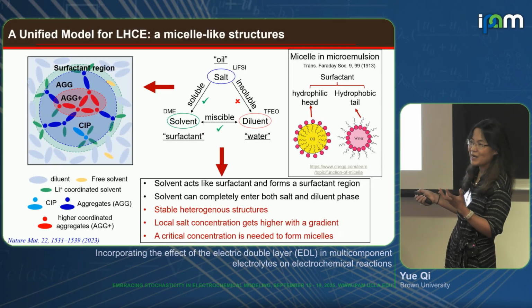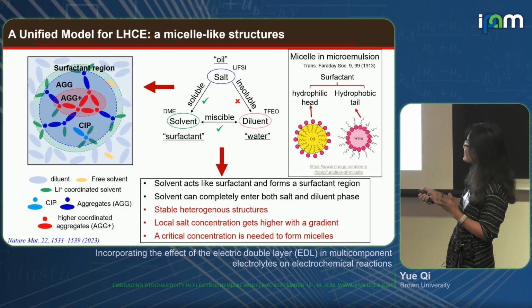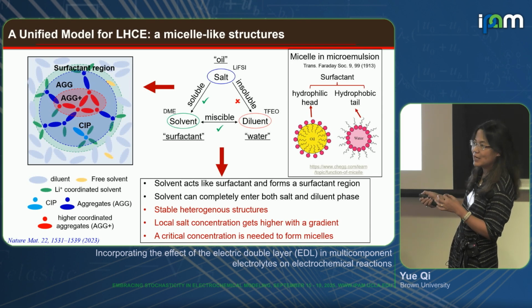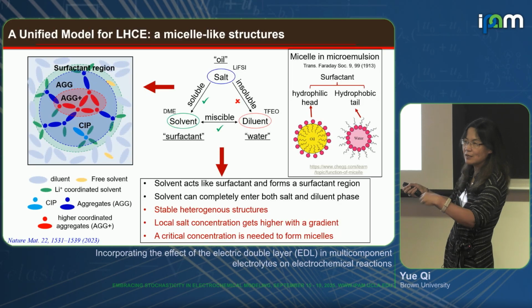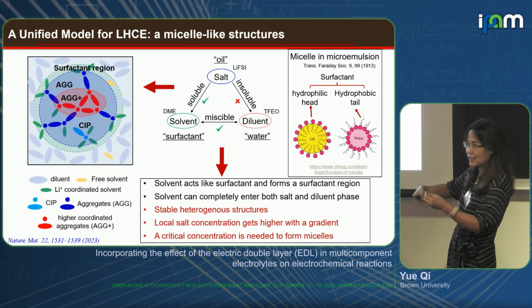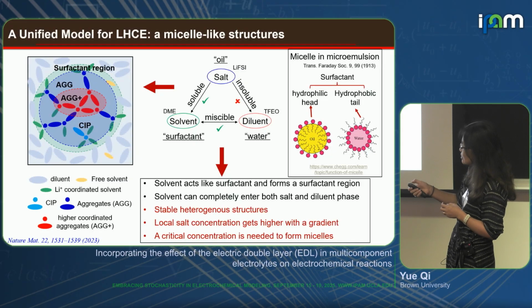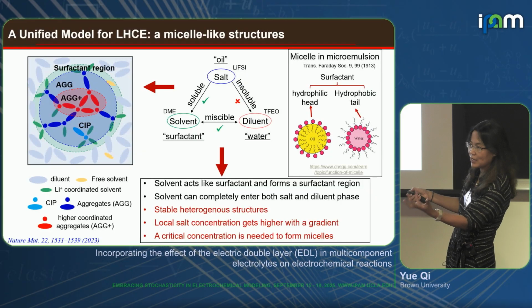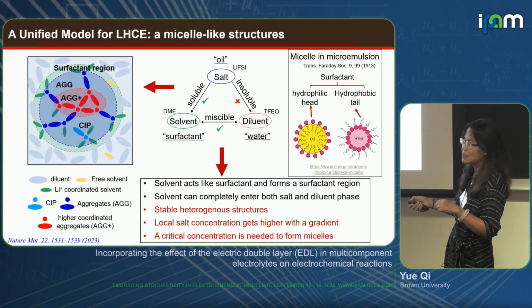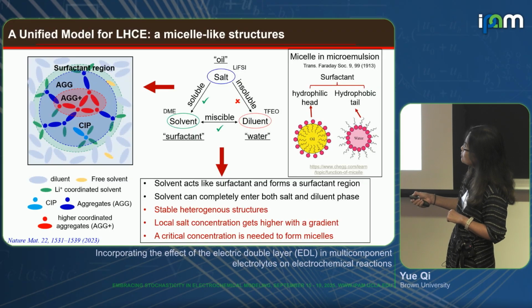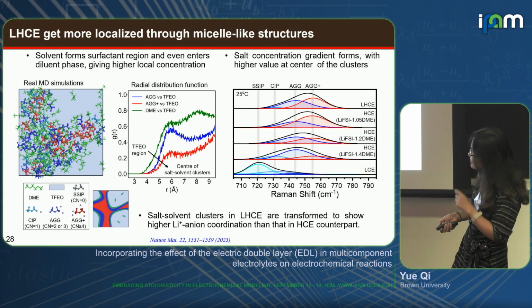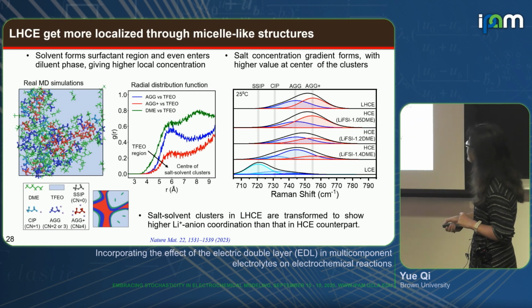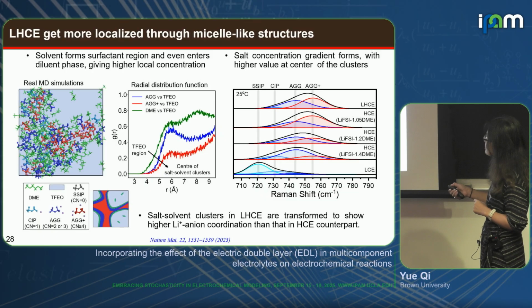But if you think about micelles, you know they don't collapse, right? This is a more stable structure. Our solvent actually is the peacemaker. It binds with the salt, and also likes the diluent, so they will naturally form some higher concentration layer at this interface and protect the salt-solvent cluster in this diluent matrix. And also, there is going to be some solvent in the diluent matrix. So that becomes an important feature. Right? So let me first explain why this is a mystery in experiment.